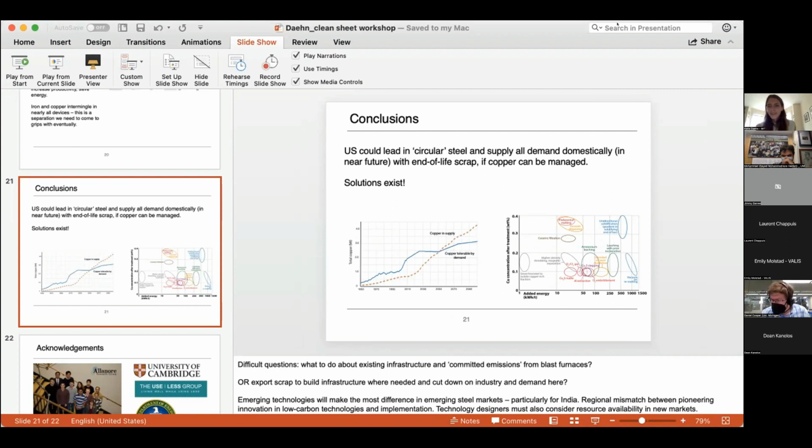Copper is a little bit more challenging when you're trying to remove it in the high temperature phase, and that's because copper tends to wick toward and wet the grain boundaries. And so we've found that it's not as simple as just heating it up and then blowing it away. It doesn't work quite like that. The best way and probably the most efficient way that we've viewed it is get rid of it before it gets into the scrap stream. But otherwise, nice presentation.